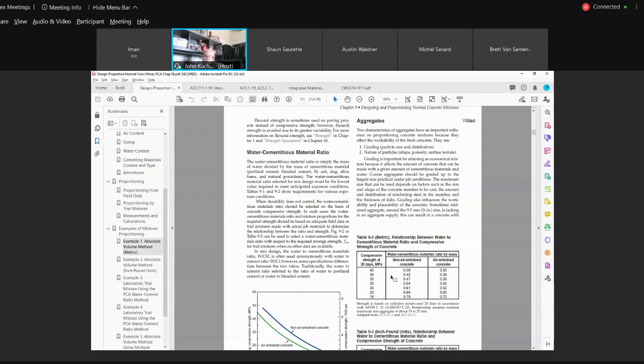So if we come up here, 40 is 0.34. And that's where on my spreadsheet, you see I use 0.34. That's lower than 0.42, and it's lower than 0.45. That's what governs. Okay? So we're using 541 kgs. Everybody okay with that? So we now have determined water, and we now have determined cement.